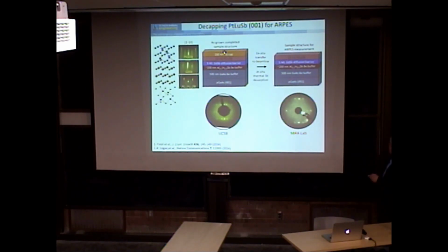So what we do, we put antimony down. If you go cold enough, we can grow antimony, and then we can heat it up, and if you go up to about 350, 400 degrees C, the antimony evaporates. But the problem we had was that this antimony reacted with the aluminum indium antimonide when we did that. So we put a little bit of gadolinium antimonide as a diffusion barrier in between. And that allowed us to go hot enough and blow it off.